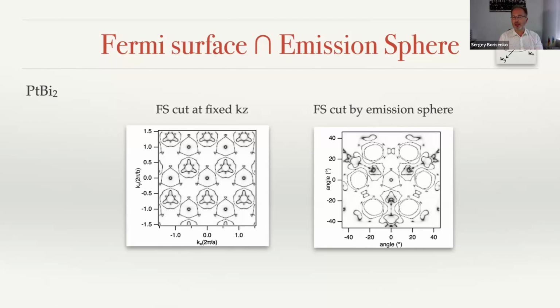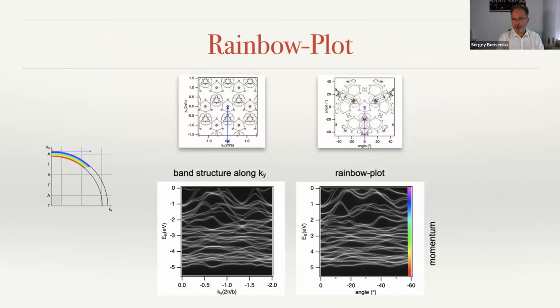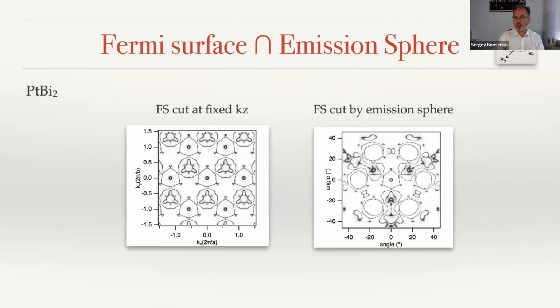And if you look at this data set, this is a Fermi surface cut at a fixed Kz. And you see this is a repeating zone scheme, and you see the Fermi surfaces which look different, which look the same when you go to the higher momentum value. And this is the data set which is reconstructed from the band structure calculations. So this is the cut of this Fermi surface by the sphere. And this is what an ARPES experiment should see. Okay, so first you see that the difference could be quite significant.